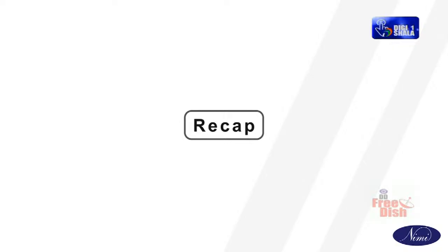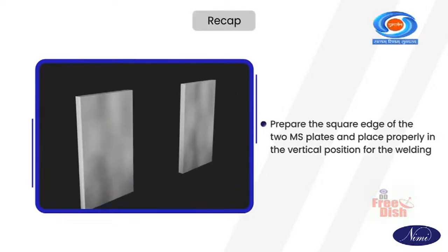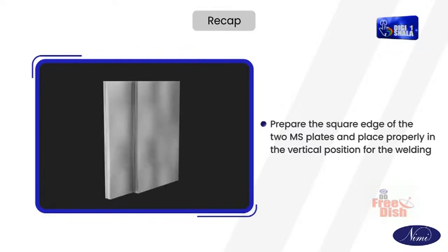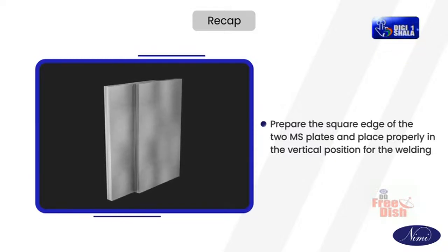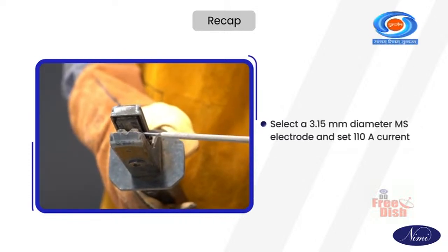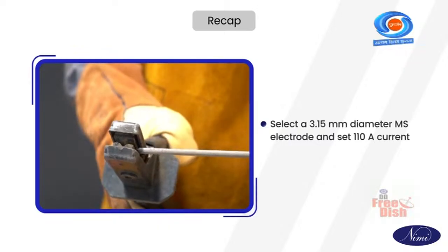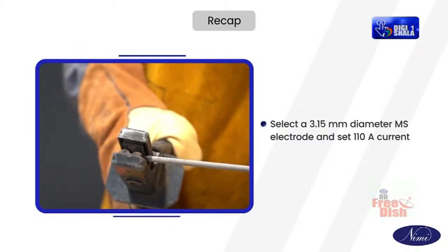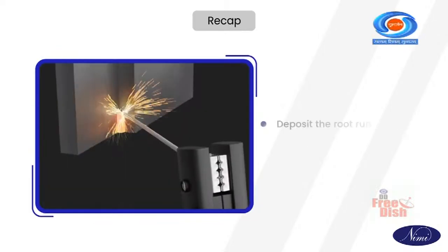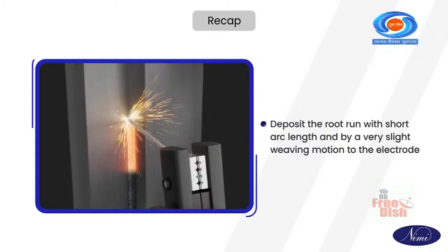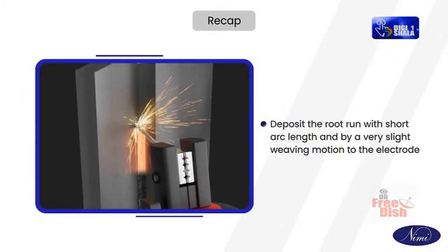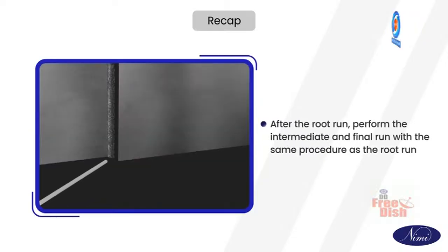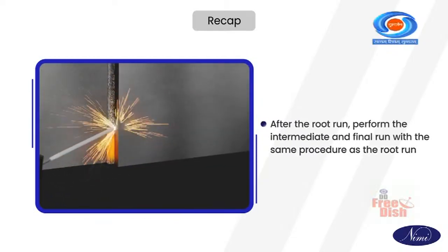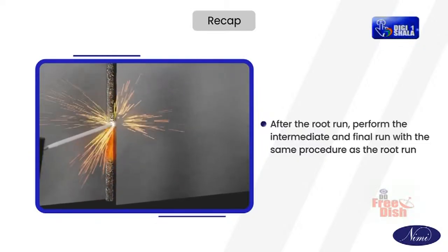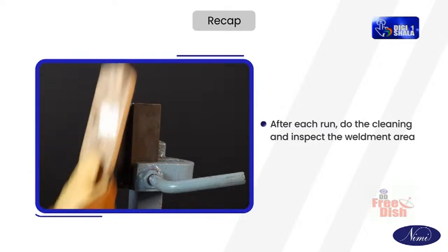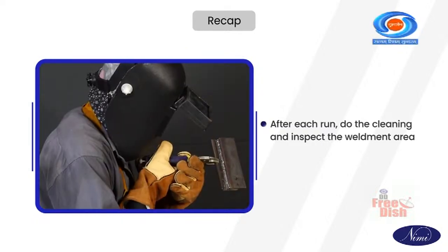Let's recap the key points discussed. Prepare the square edge of the two mild steel plates and place properly in the vertical position for the welding. Select a 3.15 mm diameter mild steel electrode and set 110 ampere current. Deposit the root run with short arc length and by a very slight weaving motion to the electrode. After the root run, perform the intermediate and final run with the same procedure as the root run. After each run, do the cleaning and inspect the weldment area.